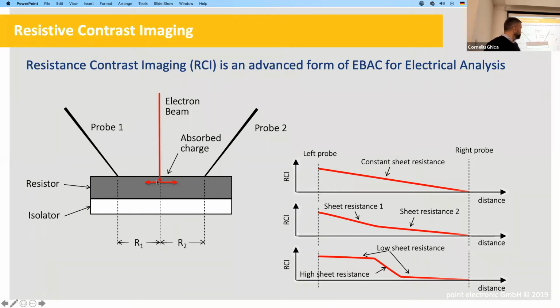And the amount of current absorbed in each of the electrical connections, which are here nanoprobes in this schematic, is proportional to the resistance between where the current has been absorbed and the distance of the probe. So that means that when the electron beam is close to probe 1, then most of the current will come to probe 1. When the electron beam is close to probe 2, then most of the current will come in this probe and not to the other.